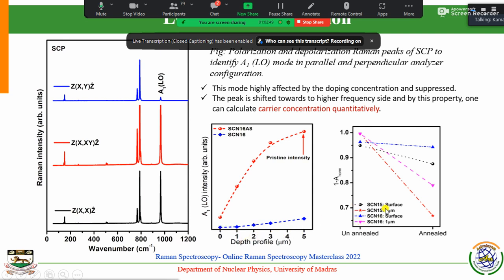And of course here you can see the low dose sample at 1 micrometer and the SCN16, the high dose sample, at 1 micrometer. Both coincide at the same point, which is the measure of damage, so the normalization of that is the damage normalized. It's saturated at 1 micrometer, which means most of the bonds are broken and the amorphous phase is saturated. Simply, after annealing we can track the variation of recrystallization by using this particular Raman mode.